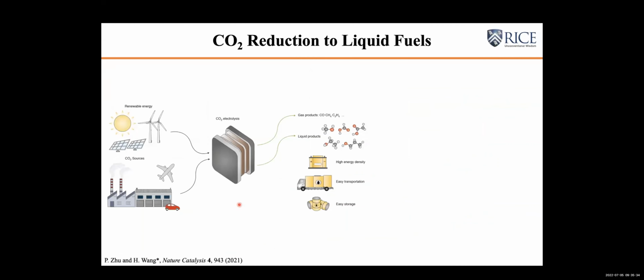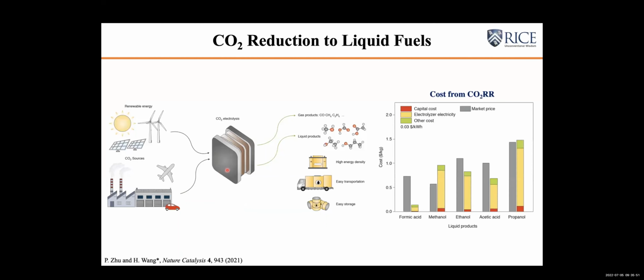Like what I mentioned, the reactor design is very important to the CO2 reduction field. This is true for the CO2 to CO generation. And this is even more important to the CO2 reduction to liquid fuels. Why we care about liquid fuels is because CO2 reduction to gas products, CO, ethylene, of course, is very valuable. Also, CO2 reduction to some liquids like formic acid, acetic acid is also very valuable, considering their very high energy densities, easy transportation, and, most important, that they are naturally separated from the CO2 stream.